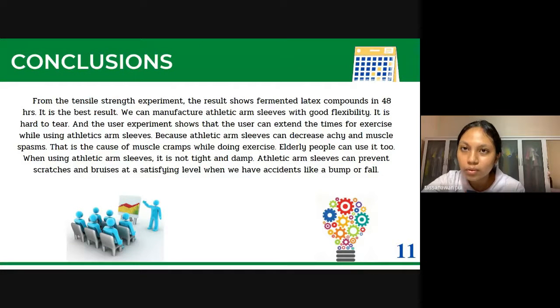Now I'm going to talk about conclusions from the tensile strength experiments. The results show that latex compound fermented for 48 hours gives the best results. We can manufacture an athletic arm sleeve with good flexibility. The user experiment showed that the user can extend the time for exercise while using the athletic arm sleeve because it can decrease arching and muscle spasms, which are the cause of muscle cramp while doing exercise. Elderly people can use it too. When using the athletic arm sleeve, it is not tight and damp. It can prevent scratches and bruises at a satisfying level when we have an accident like a bump or fall.